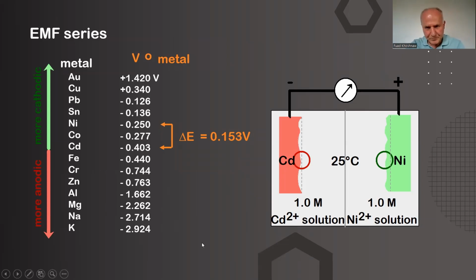Usually, in general, the elements at the top are cathodic, and the ones going down are anodic. To avoid galvanic corrosion, we need to choose two materials that are not far from each other. Because if delta E, the voltage potential difference between these two, is high, then the force pushing the electrons from anode to cathode will be high, and the corrosion rate will be high. But when the materials are close to each other in this diagram, then the potential difference will be low, and the corrosion rate might become low as well.